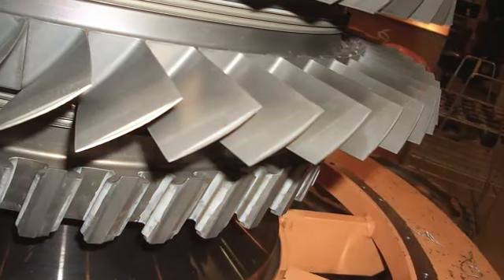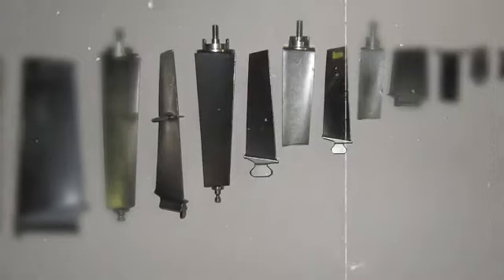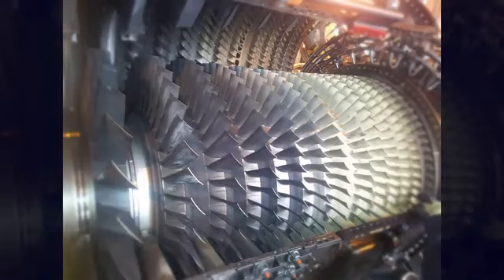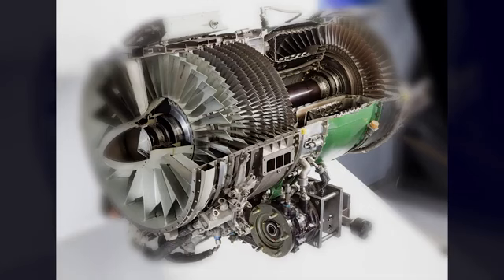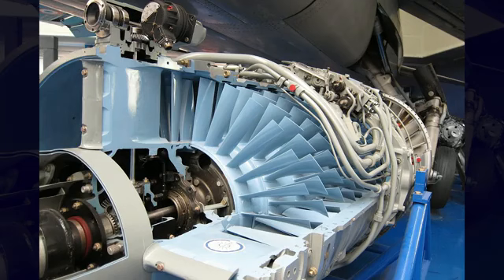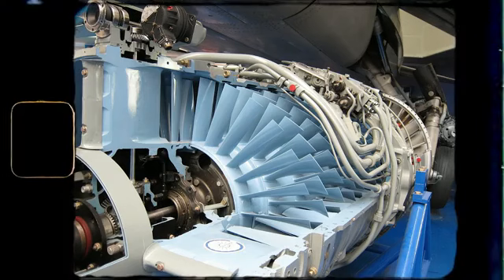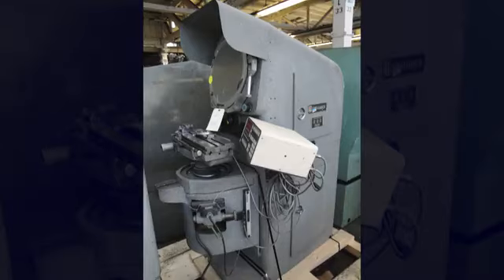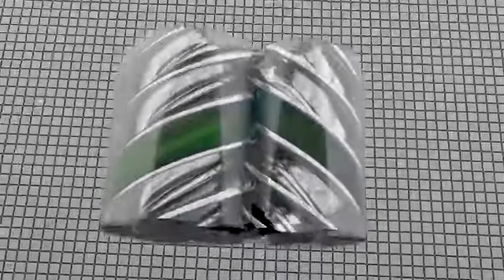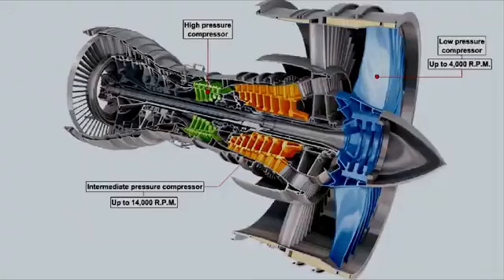Then comes the high-pressure compressor. Smaller blades, tighter clearances, higher stakes. The gap between the blade tip and the surrounding casing is sometimes less than half a millimeter across a disc that may be 400 millimeters in diameter. Too wide and efficiency drops measurably. Too tight and thermal expansion during operation causes the blade to contact the casing. Getting this right requires custom laser measurement tools and repeated trial fitting.